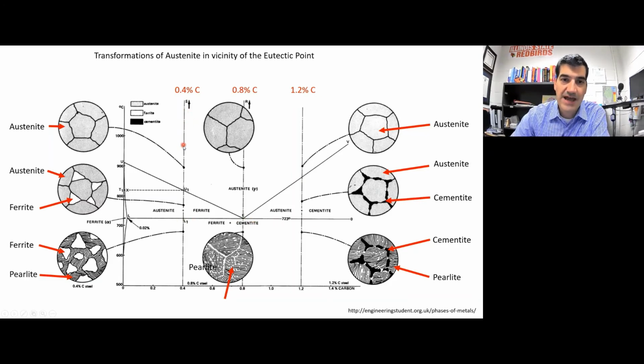And here's a diagram of what happens if you cool down a steel with 0.4% carbon. Initially, you've got all austenite. Then you cool it down below the upper critical temperature. You've still got some austenite, but now your ferrite grains are growing and they're transforming those austenite grains into ferrite grains. Then we cool it down some more below the lower critical temperature. And now we've got ferrite grains as well as perlite grains because there was more carbon than the ferrite grains could absorb. So some of that carbon had to diffuse somewhere else. It had to migrate, had to go somewhere else. All right, and that process is slow.